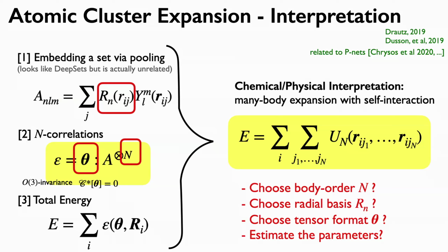The tutorial is going to be purely for linear models, because then you can do the parameter estimation in 2 minutes or even less. But, for example, earlier we were chatting about the code that Ralf Drautz's group wrote, and they use a Tucker format for that tensor, and what that allows you to do is use basically fewer embeddings, fewer features. It sort of compresses the whole model a little bit. It's more expensive to estimate the model, but then you get a smaller model in the end that is cheaper to evaluate. Where exactly is the sweet spot here?